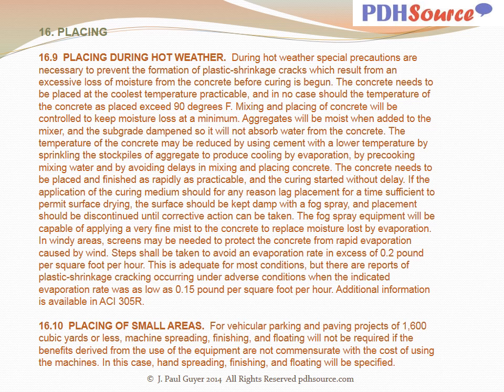Steps shall be taken to avoid an evaporation rate in excess of 0.2 pounds per square foot per hour. This is adequate for most conditions, but there are reports of plastic shrinkage cracking occurring under adverse conditions when the indicated evaporation rate was as low as 0.15 pounds per square foot per hour. Additional information is available in ACI 305R.